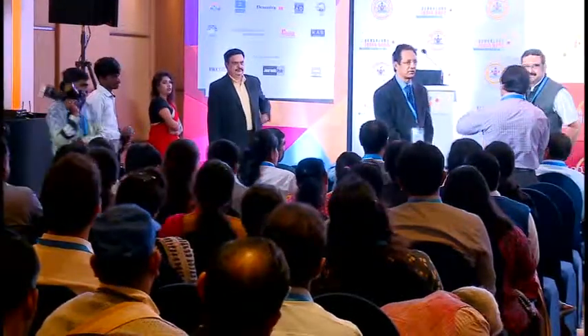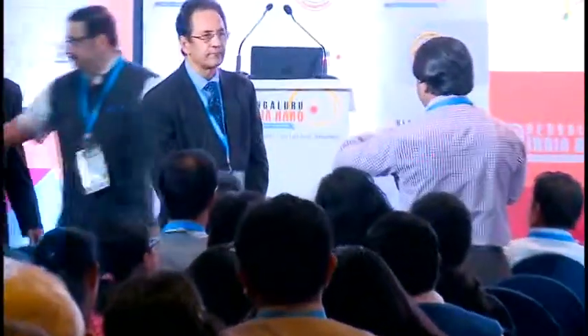The deposition is very thin. Very, very thin. Molecular size deposition I'm talking about. So how do you achieve it? Deposition, film making. We spin it off. It's very thin. It has to do with the viscosity of your solvent and spin speed, and so we make it anything from 10, 20 nanometers all the way up to about 80, 90 nanometers. Those are the actual range of work.